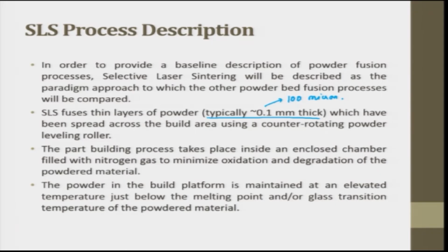The part building process takes place inside an enclosed chamber, whereas in the previous schematic diagram it was open. Generally we do it in an enclosed chamber, and in the enclosed chamber we maintain a temperature and fill it with nitrogen gas to minimize oxidation and degradation of the powder material. Because whenever there is heat, oxidation easily happens. In order to avoid this, we put the part in a chamber and fill it with nitrogen gas, which is non-reactive. The powder in the build platform is maintained at an elevated temperature just below the melting point or glass transition temperature of the powder, such that it sticks with the previous layer.